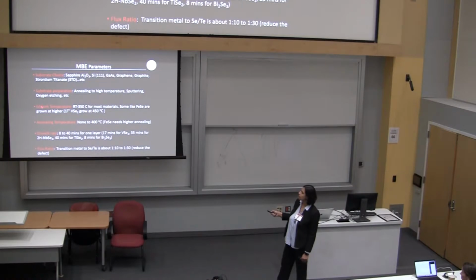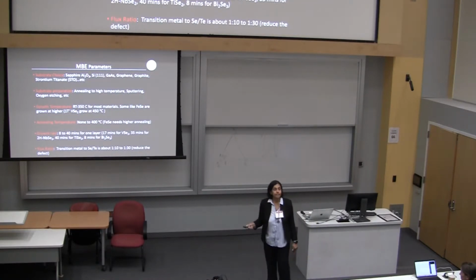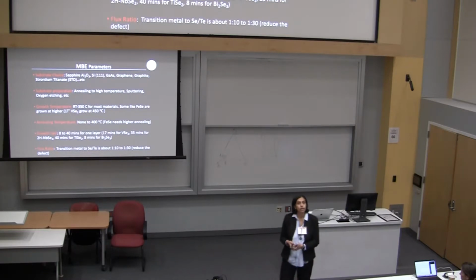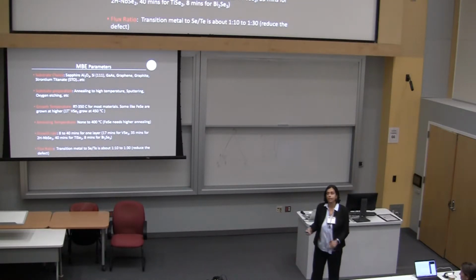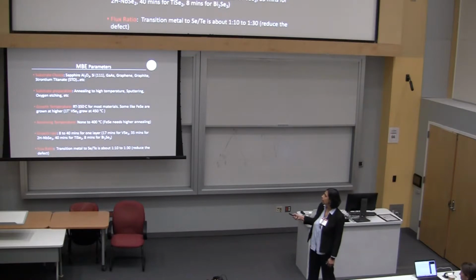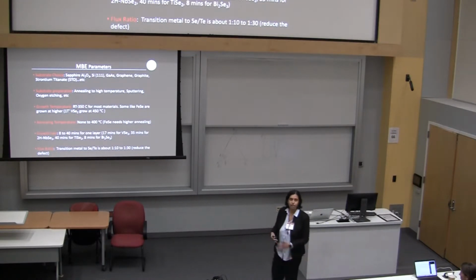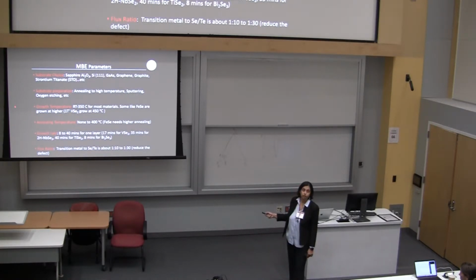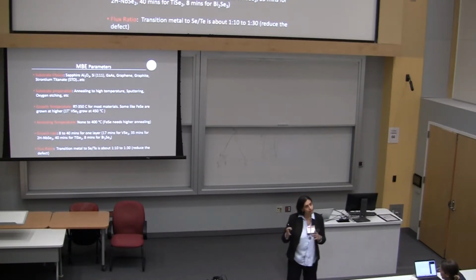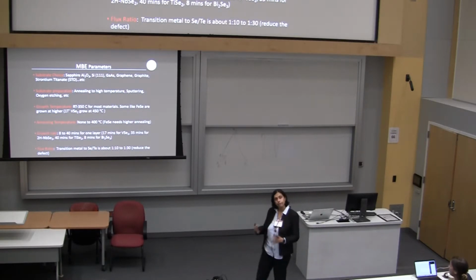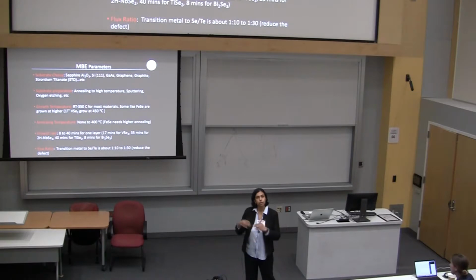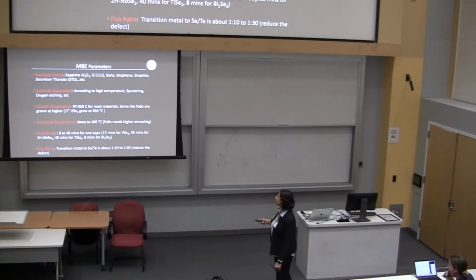And the third important thing is the growth temperature. The nice thing about chalcogenides is that they grow at pretty low temperatures. So you can grow many things at around 300 degrees. FeSe, which is not a dichalcogenide, I just mentioned this because a lot of people are interested in this. It actually is grown at a much higher temperature. So vanadium diselenide, for example, is one of the highest temperature materials. We've actually grown it at 450 degrees. And we found that depending upon the growth temperature, you can get different phases. You can either go into the 1T phase or the 1T prime phase or the 2H phase.